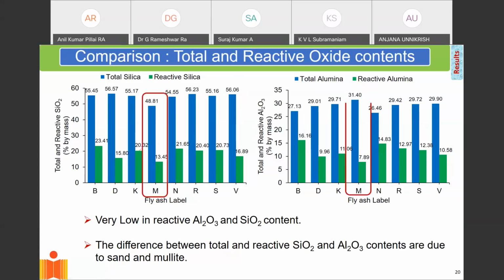And basically, I just show you this. This is one particular fly ash which is being used quite a bit. And you find that it has only 13% reactive silica, but it's being used quite a bit as cement replacement. So we really need to understand our chemistry in order to optimize how much silica, how much fly ash we